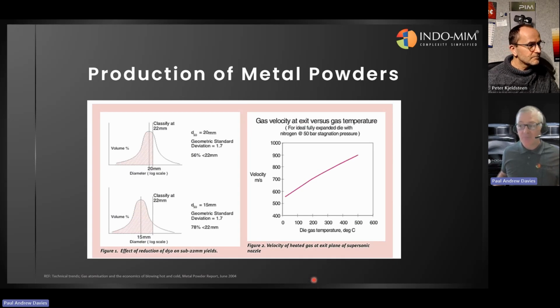The die gas temperature can have an influence on the velocity as well, and basically the relationship that has been found more than 20 years ago, actually from 2004, was that as you increase the gas temperature up to 500 degrees, for instance, then the velocity of the gas increases as well, and that was basically found to reduce the average size, or the median, the D50 of the powder particles. So in this case, you can see that the D50 went from 20 micron down to 15 micron, and also increased the yield of fine powders as well.